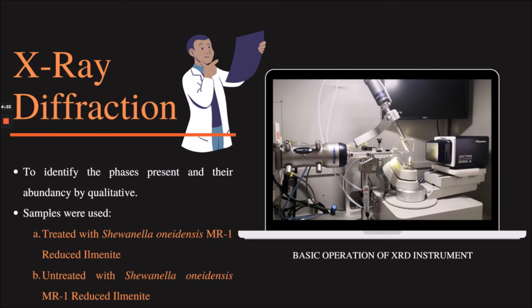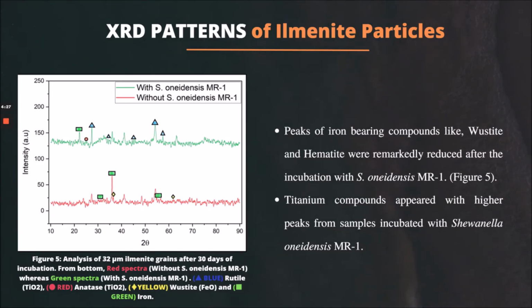The final test was the X-ray diffraction method. We compared the dominating crystal phases present in each sample. As you can see in figure 5 on our left, the red spectra without Shewanella was dominated by iron and iron-based compounds, but the green spectra, which is on top, where the ilmenite was treated with Shewanella, displayed more titanium compounds such as rutile. To summarize, the iron oxides which suppressed the titanium compounds were leached out remarkably by the presence of Shewanella oneidensis MR1.